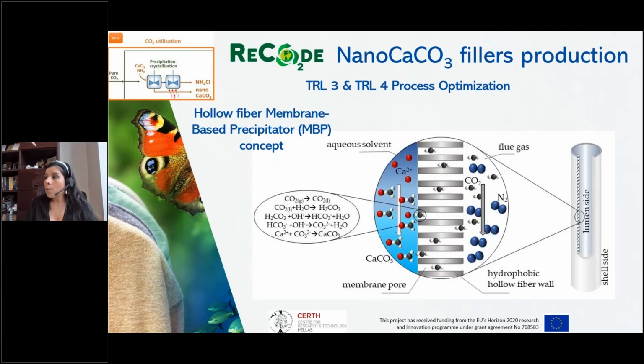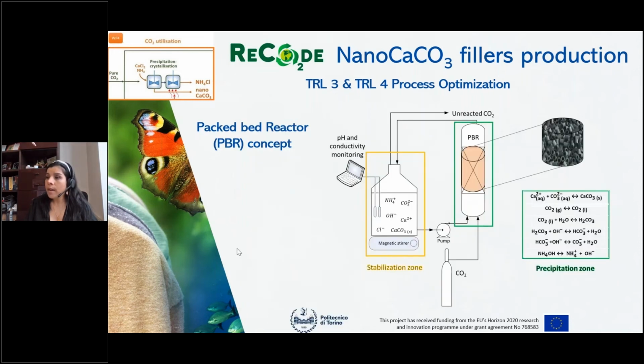And we have also optimized 2 different kinds of reactors. A first kind of hollow fiber membrane-based precipitator that enhances the contact between the gaseous phase CO2 and the other precursors of the calcium carbonate. And we have also developed a new concept of packed bed reactor for this crystallization precipitation system.